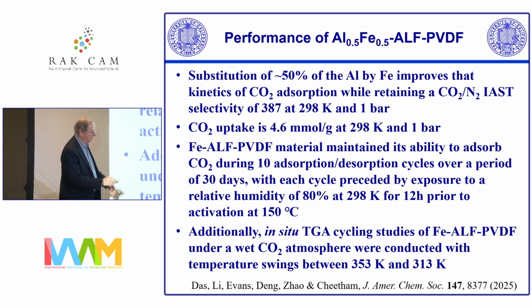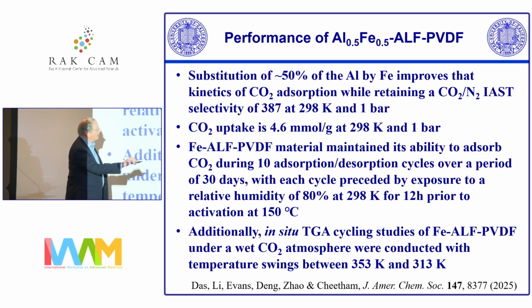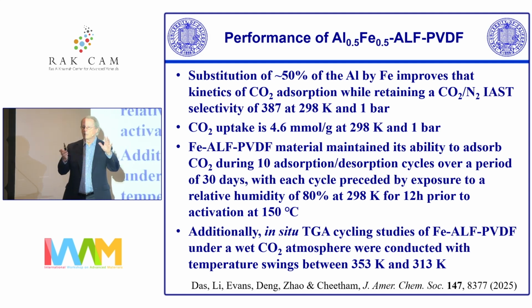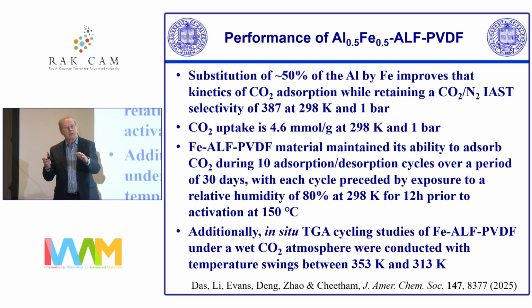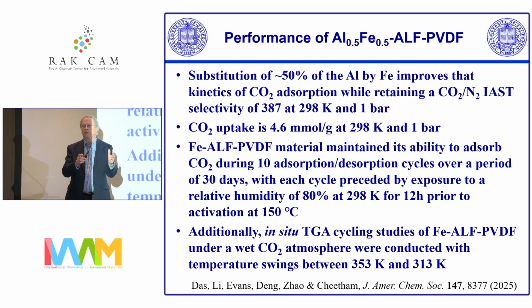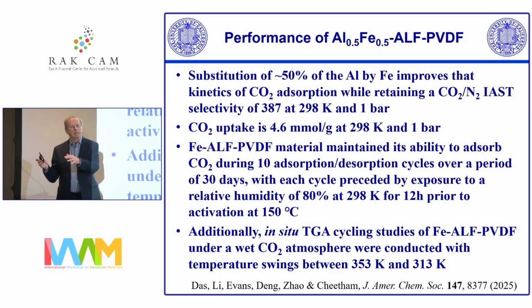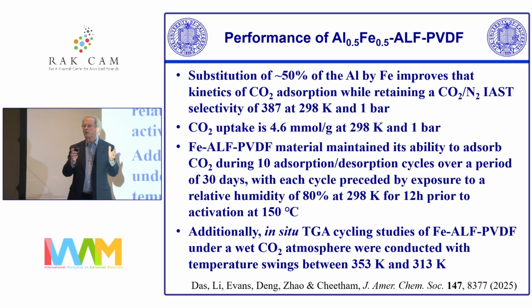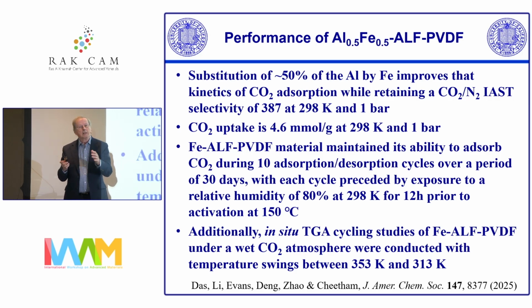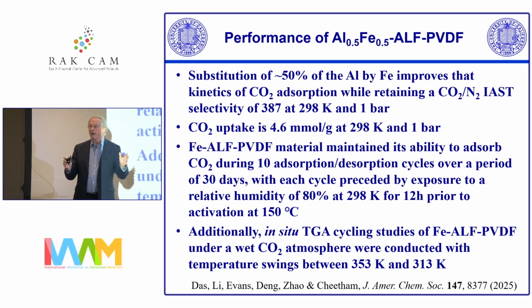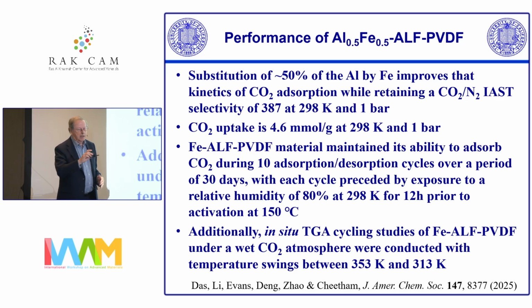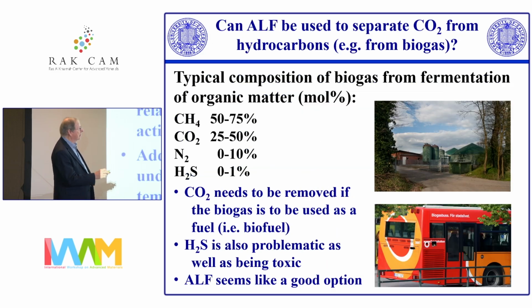One other thing that's worth pointing out, if we make solid solutions of aluminum with iron, then you can get enhanced performance. The pure iron compound you can't activate. If you go to something like 50-50 or up to about 70% of iron, then you get better kinetics than we get with the pure aluminum compound, and we preserve the performance. And of course, iron hydroxide is also very cheap.